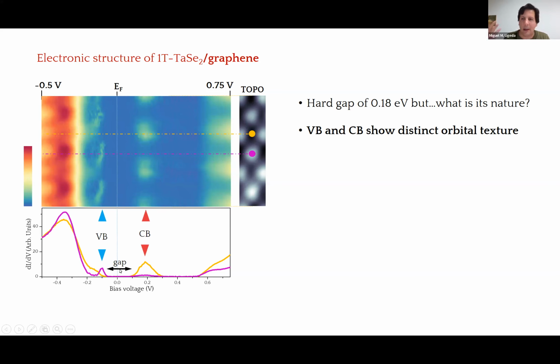There's a hard gap of around 0.2 electron volts, and this is the valence band. Here, this is the conduction band. They are in opposite phase. When this sharp resonance is visible, then the conduction band is basically gone, and vice versa. But the point here is, are these two the lower Hubbard band and the upper Hubbard band of a Mott insulator that enables the formation of a quantum spin liquid?